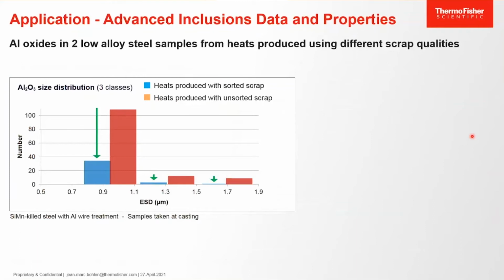An interesting application was obtained with a customer. We measured two of his low alloy steel samples. Actually, we measured the aluminum oxides to check their distribution. The two samples were produced with different scrap qualities. The first one in blue is a sample taken from a heat produced with sorted scrap, so in principle scrap with more purity. And the red one is a sample from a heat produced with unsorted scrap, so scrap of different sources. So the red one is in principle cheaper than the blue one.